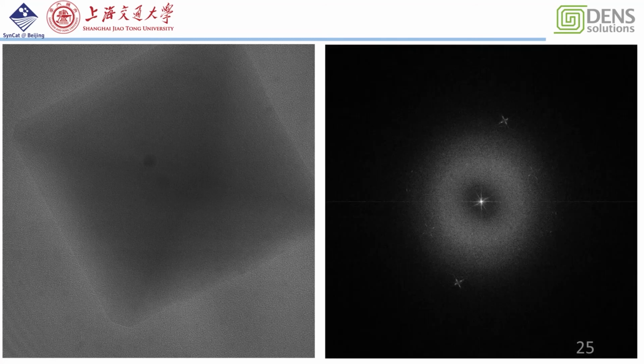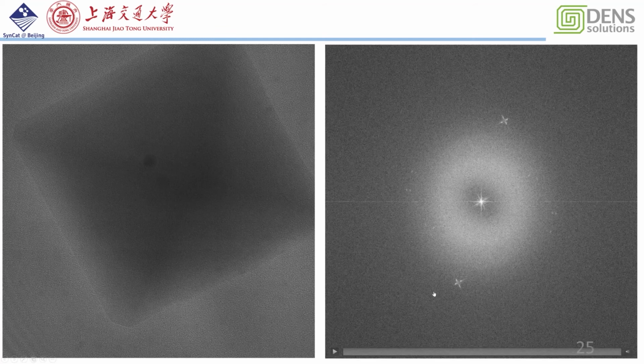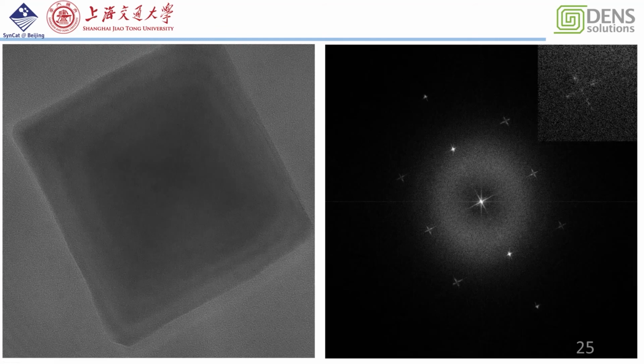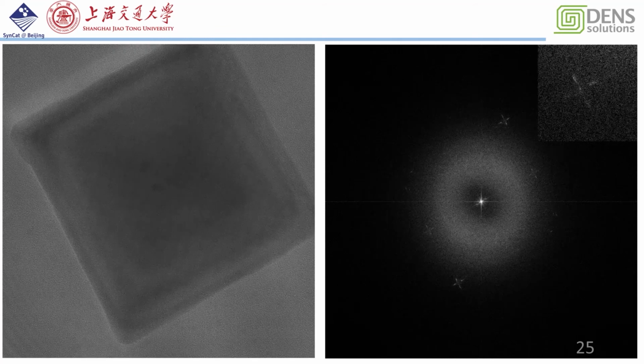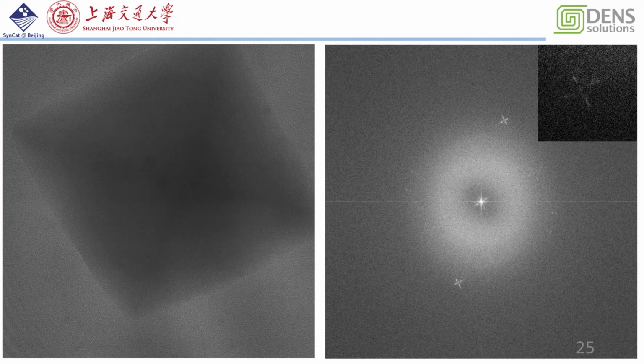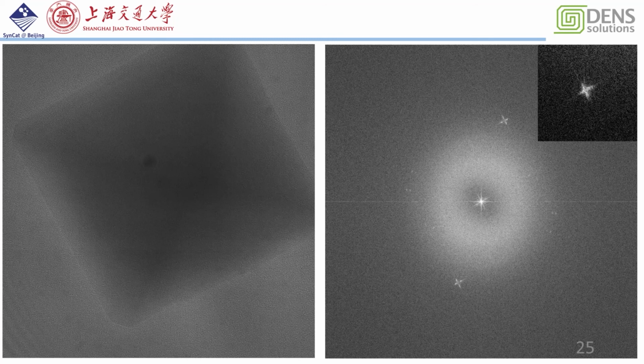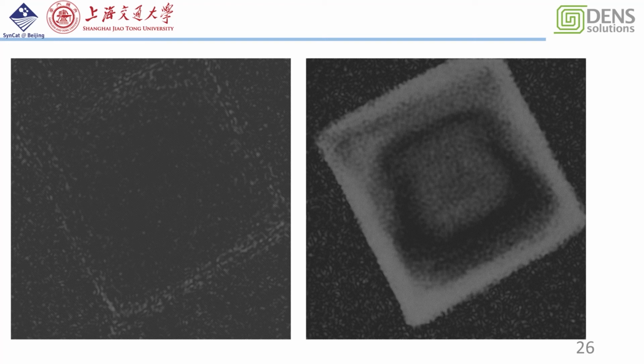If we look at this point, we can see this structure changed, and this modulated structure changed during the reduction process. So clearly, the new species formed on the surface of the octahedral iron oxide magnetite nanoparticle. And due to the overlapping of the new species and the magnetite, the moiré patterns changed. But this process changes periodically. So once this new species was removed from the octahedral magnetite, the pattern changed back. If we just choose the pair of the patterns to do the IFFT, we can clearly see how the surface reconstruction happened, and it gives very clear information about how the bulk and the surface changed during the reduction process.